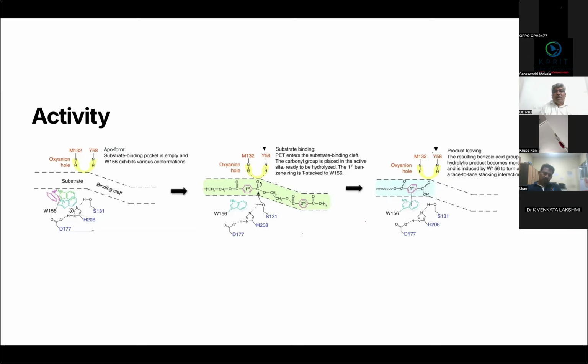The keto group of the PET properly aligns with the oxyanion hole, and the tryptophan 156, as you can see in the left side active site, shows various conformations. But as soon as the PET is present in the active site, the tryptophan 156 is stabilized, and it is stacking with the aromatic ring of the PET. Once they are properly aligned, the serine 131, which is part of the catalytic triad, will do its activity, and there is a cleavage of the PET chain, and the monomer is released from the active site.